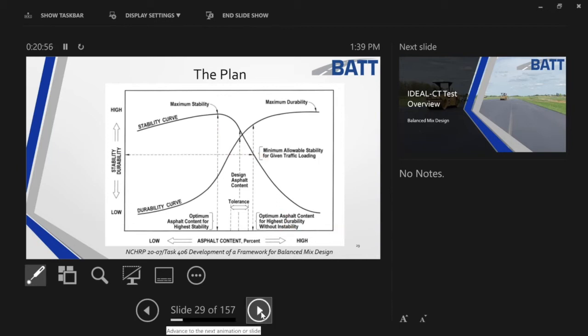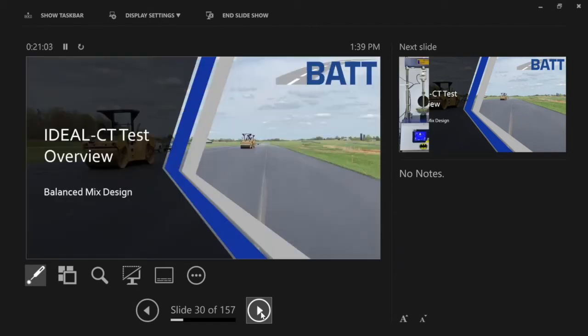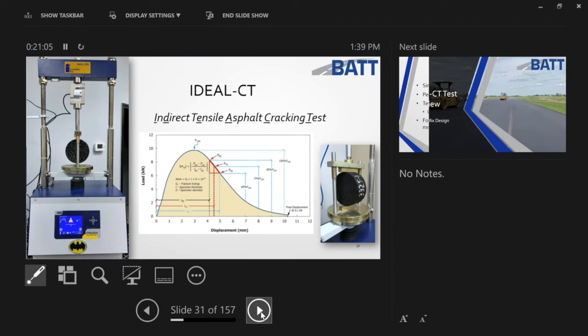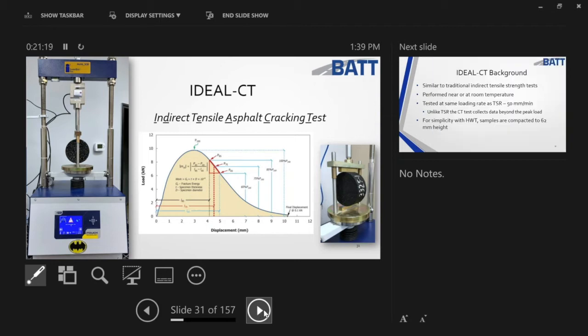So what we're going to do is a quick overview, and I mean a quick overview, of the ideal CT test, and then a quick overview of the Hamburg test. Ideal CT, and Joe, I'm just going to ask you to keep up with me on these slides. Ideal CT is a simple monotonic test where I load the sample, and as I load it, I gather this curve that you see here, and I take the energy under that curve and divide that energy by that slope. The reason it's important to divide it by that slope is, again, this is an index test, because I'm not truly getting the real fracture energy by pulling the sample apart directly. I'm doing it indirectly. Joe's pointing out my Batman symbol there, Joe.